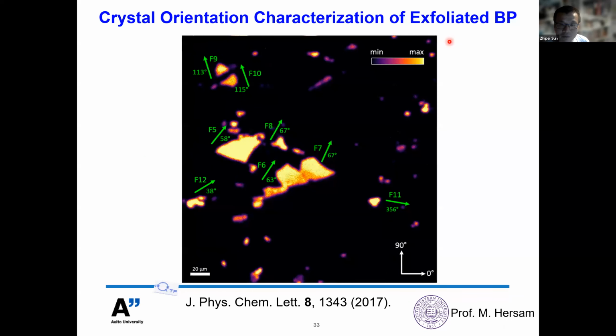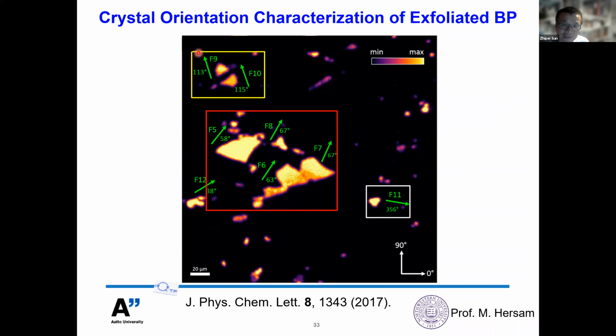Then if you look at a little bit more detail, you will find something very, very interesting. For example, if you look at all these crystal orientations of the different flakes, you can easily see that those flakes were produced at the same time when we did the mechanical exfoliation. So this is something really interesting. You can use third harmonic generation not only to look at the crystal orientation, but also to tell how many flakes are produced at the same time when you do the mechanical exfoliation.